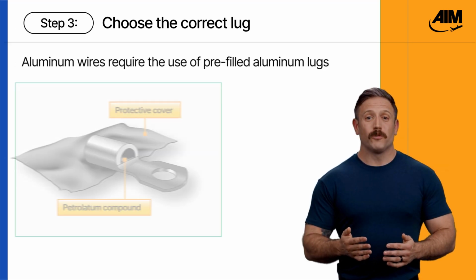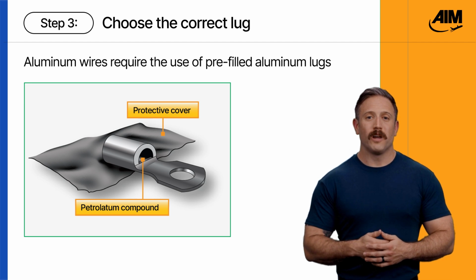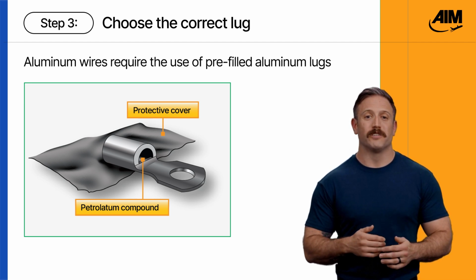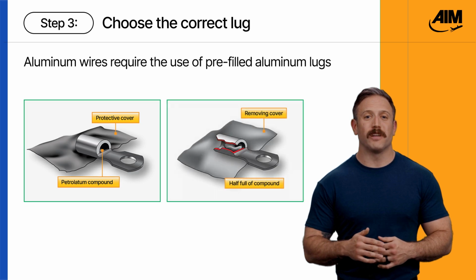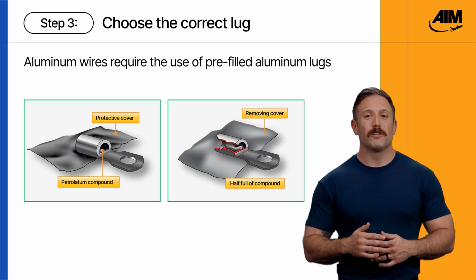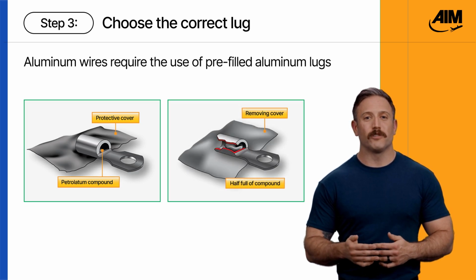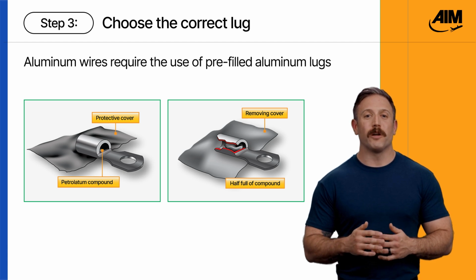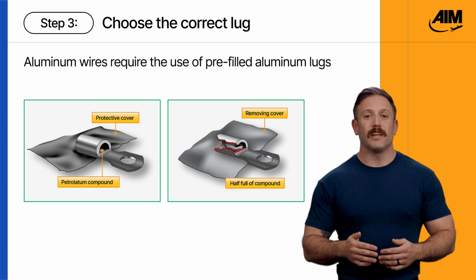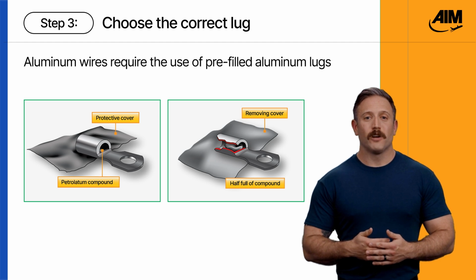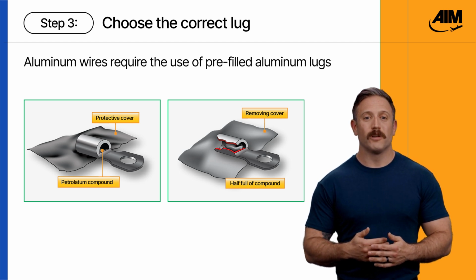If you are working with aluminum wires, use aluminum lugs that come pre-filled with a petrolatum zinc dust compound. This compound chemically breaks down surface oxidation during crimping and seals the joint afterward. Don't wipe out the compound, and don't remove the internal plastic seal. These are critical to the joint's long-term stability.